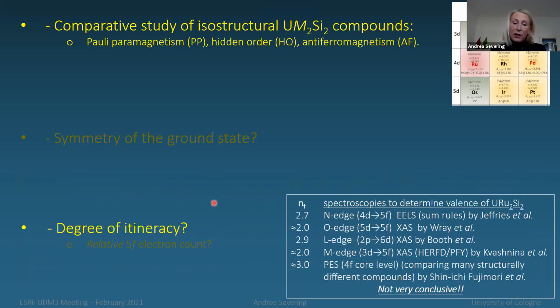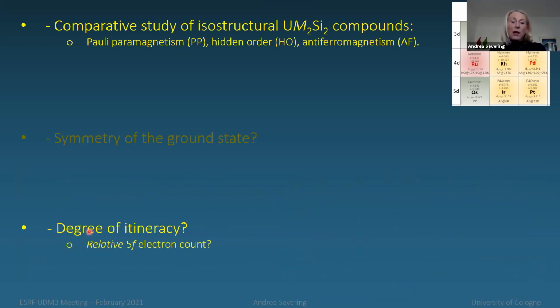And this is why we decided, well, we are not aiming at an absolute filling of the 5f shell. No, we rather look at a relative 5f electron count. And this is why we are comparing these isostructural compounds with very different ground state properties. However, even then, we have to make sure they all have the same ground state symmetry, because the ground state symmetry is important for the way the ground state couples to the conduction band.